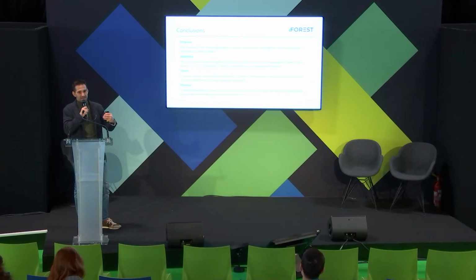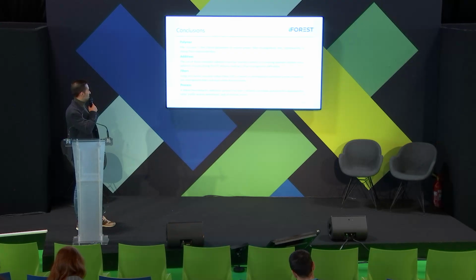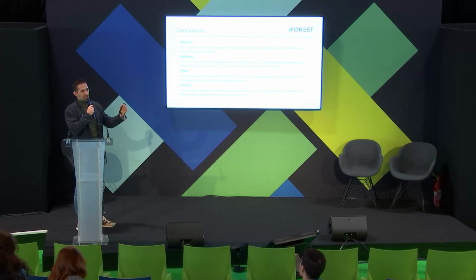But we achieve enough viscosity, a really nice viscosity for that. Regarding the additives, the use of flame retardant additives must be carefully limited. Since we increase the amount of flame retardants, in the end, this is a load. This is an additive that increases the viscosity of the whole system. So if we increase the viscosity, we have the first problem, which is that we cannot impregnate the fibers properly. We lose this impregnation facility, let's say. So we have to limit the amount of additive that we add, the flame retardant, although we reach levels of flame retardant that improve quite a lot the fire performance of these composites.